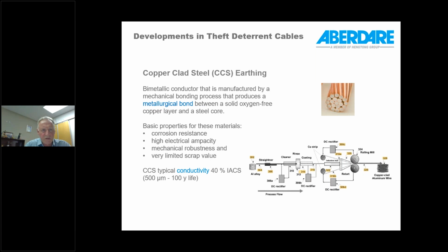So just a little bit more detail on copper-clad steel earthing. There's a thin layer of copper which is applied over a steel substrate, and this kind of system relies on a metallurgical bond between the two metals, and that's the reason why it can't be separated mechanically. You have to use a chemical process if you were to try and separate the two metals. This is not plating, it's not an electrolytic process. It's a mechanical means of applying copper to a very clean substrate of steel, or aluminium alloy in the case of CCA.